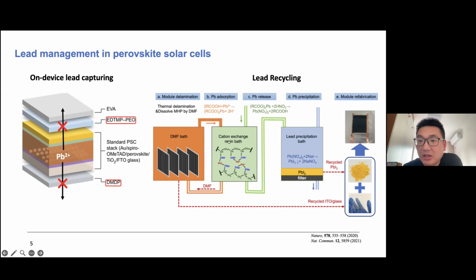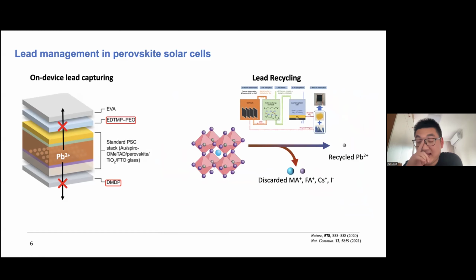This one is a very typical example of lead recycling. They dissolve the degraded solar panel and then use a cation exchange resin and some chemical process to extract just the lead ions, to get the recycled lead, and then react it with sodium iodide to get lead iodide, and then use it to fabricate a new solar panel. But in this lead recycling, most other ions have been discarded. We think it's not enough, but it was already the best work reported at that time.